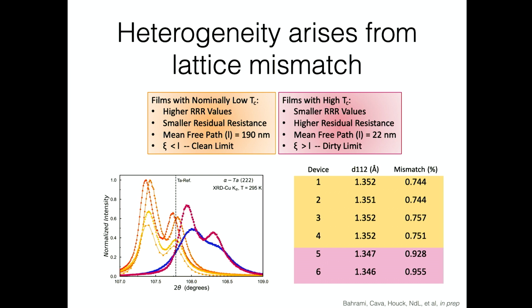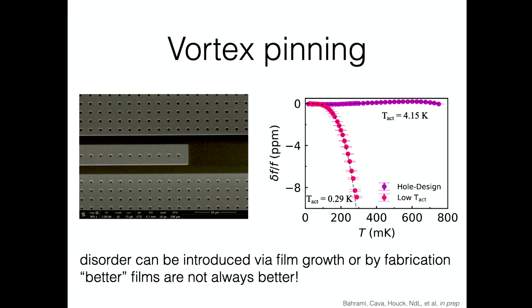So a natural hypothesis now is that these are vortices. So if I have superconducting vortices that thread through my film, if you make a really, really nice film, there's nothing to pin these things so they can move around and also give me losses. Okay, so it looks like we can pin the vortices with disorder in the material. We can also do things like just explicitly pin them by doing fabrication. So now this is a film that started out like one of these low activation energy, vortex loss films. And all we did is take it and drilled holes all over the place. And we were able to convert it into a high TC film.